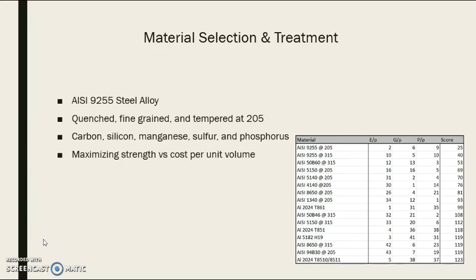When considering heat treatment, it is important to consider quenching, tempering, and sometimes fine graining. But in steels, like ferrous metals, steels have a lot of phases that it can go through depending on how you quench it, how you temper it. It goes for how you etch it and stuff like that. And in this case, this one was quenched and fine grained and tempered at 205 degrees Celsius, meaning that for this specific material, we would need to quench, fine grain, and temper it at 205 degrees Celsius to produce the specific shear modulus, the yield strength, and all that needed for this application.